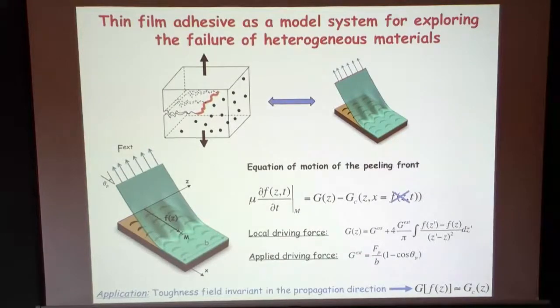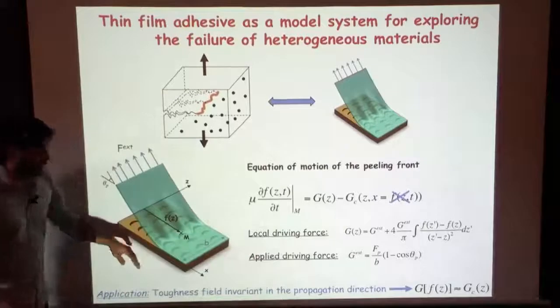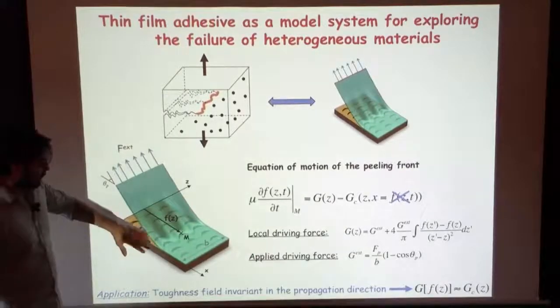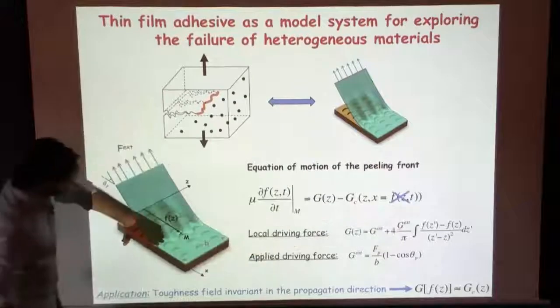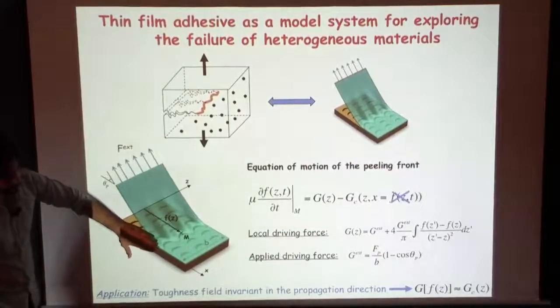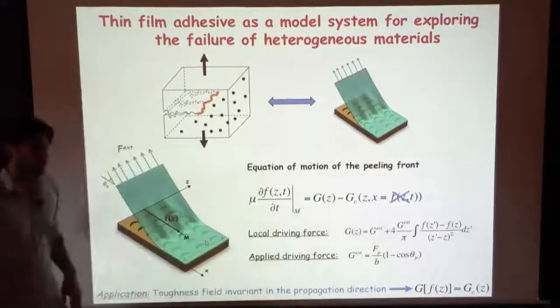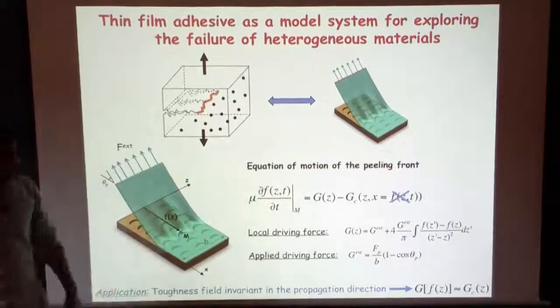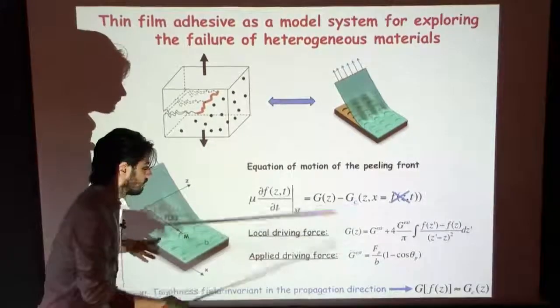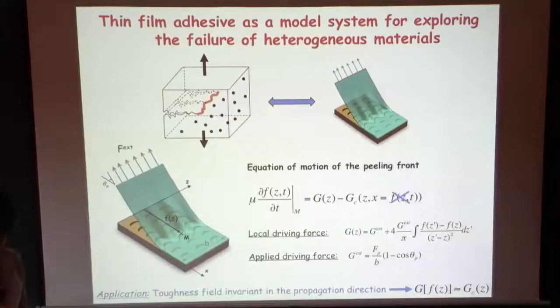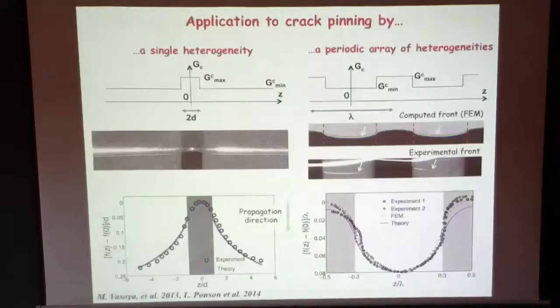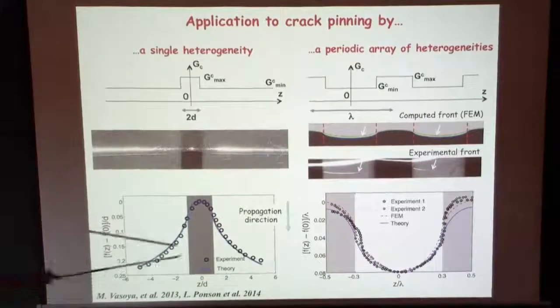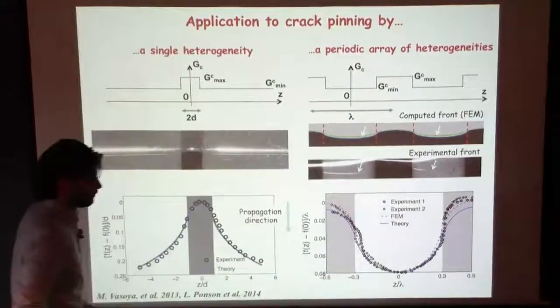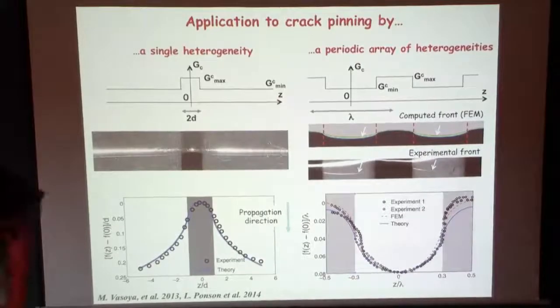From the plate theory, you can actually go into it. No, this 4 is nothing really universal. If you go to a smaller angle, you will have an effect of stretching, and then this prefactor is going to depend on your peeling angle. So there is nothing really magic. As long as the peeling angle is larger than some critical peeling angle, you get 4, but it can change with the peeling angle at small peeling angle. And the shape is supposed to be a logarithm as you move away. Next slide. Yeah, that's it. Here it's a logarithm. Here there is not a simple form you can write.